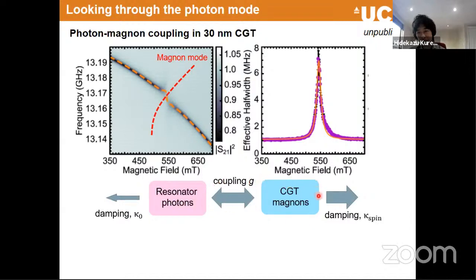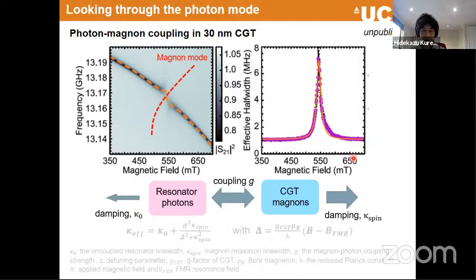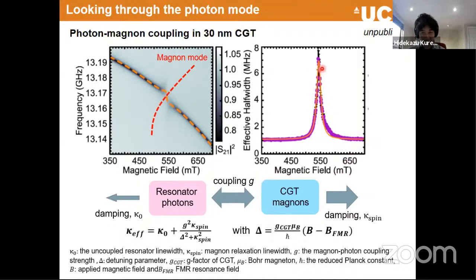Because the damping or relaxation of the magnon is larger than this, once we pump this system through the resonator, pretty much all the energy is drained by this channel. What is observed is a huge increase of the line width from about 1 megahertz to 8 megahertz. This Lorentzian peak can be fit by Lorentzian behavior, and we can extract the coupling strength and also the relaxation rate of the magnon. So that's something we can use as a tool to study the thin film flake.